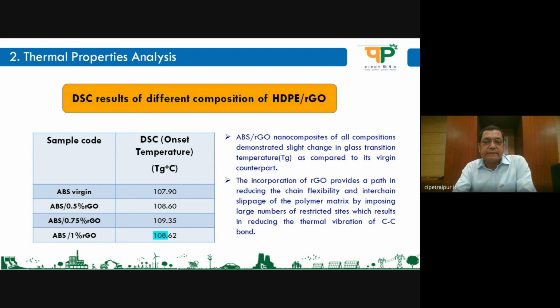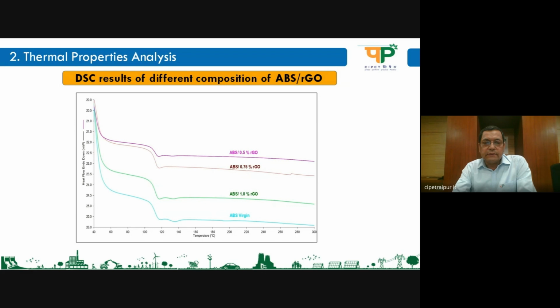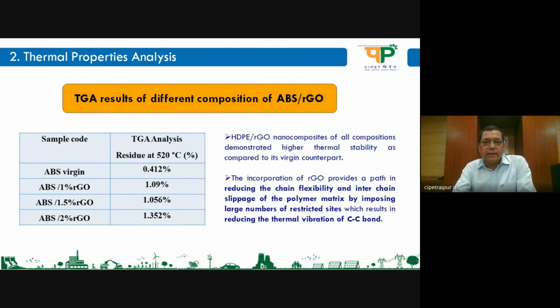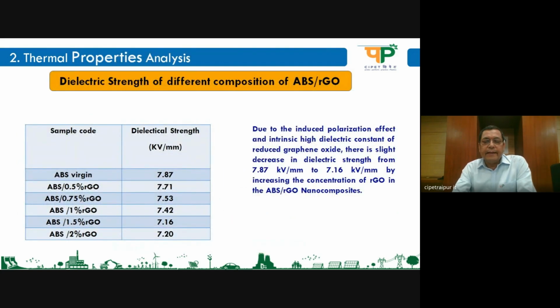Similarly, in DSC analysis, if you see, with 1% RGO the DSC is also stable. We can say 108.62, which was 107.90, so not much deviation is observed in DSC. This is the DSC curve. In TGA, ABS virgin is 0.412%, but here we are observing higher thermal stability due to the C-C bond, carbon-carbon bond, which is due to reduced graphene oxide. This is the graph of TGA.